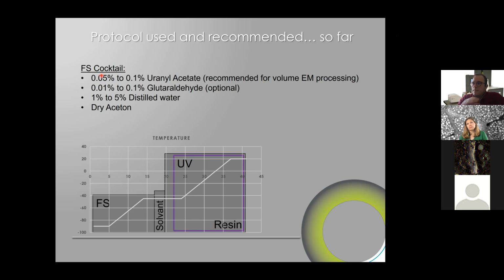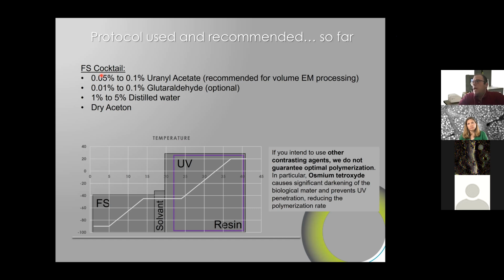Then the temperature path was always set to be the same because, again, we want to remove the variability, and we'll come back to that point later on today. And the first thing that we did not want to test was to put osmium tetroxide. I know that many people like to use that because it also increases a lot the contrast in the membrane. It's important in SEM. But the same as for the Lowicryl, the resin polymerizes with the UV. So we did not recommend using osmium tetroxide in this resin, although we cannot prevent someone from doing it, and we'll come back to that point later on.